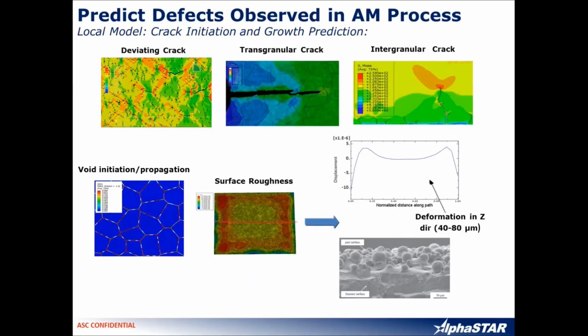In this slide, I'm showing the predicted defects observed in the AM process. For the local model, we look into the crack initiation and crack growth predictions. On the upper left, you see the deviating cracks, the transgranular crack, and the intergranular crack. This is what we can predict using our AM process software. On the bottom, you see the void initiation and propagation. We can predict the surface roughness, and here's an example of the surface roughness predicted and compared with the bottom right test.